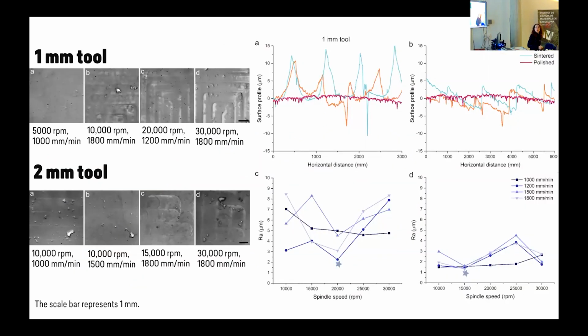So again, boring stuff. You have to do different diameters of the tools. 1 millimeter tool, 2 millimeter tool. You basically check the surface profile. You try to get the surface as smooth as possible before and after sintering, and then you check your material removal rate and such. Again, it's not something that I'm super proud of, but it needed to be done because my aim for the rest of my academic career is to convince the ceramic industry to shift to this kind of formation of green bodies rather than all the stuff that they do, where they have substantial amounts of material leak as well as energy leak.